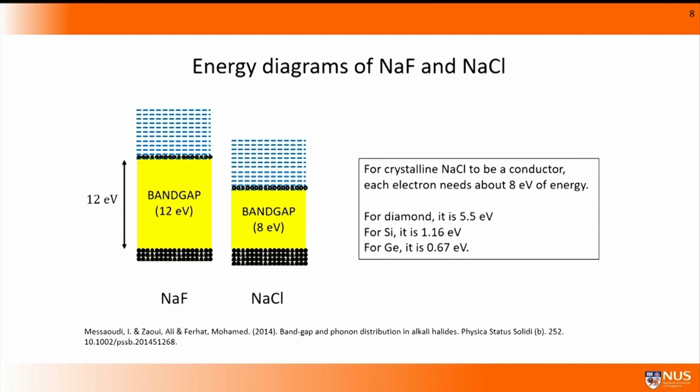So if I were to ask the following question: silicon at room temperature contains 1.5 times 10 to the power of 10 conduction electrons per cubic centimeter. How many holes in the valence band does the piece of silicon have at room temperature? The answer is exactly the same number, right? Because every single one of those electrons in the conduction band started off in the valence band and moved to the conduction band through thermal excitation, leaving behind a hole. Now, silicon has a gap